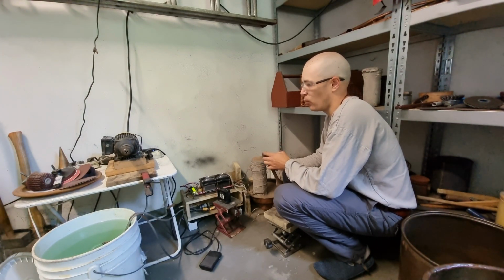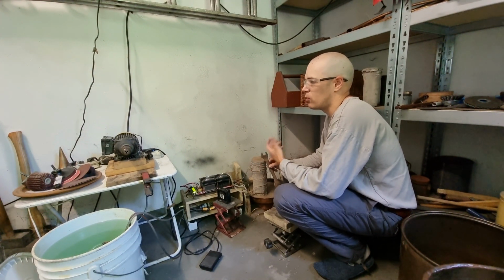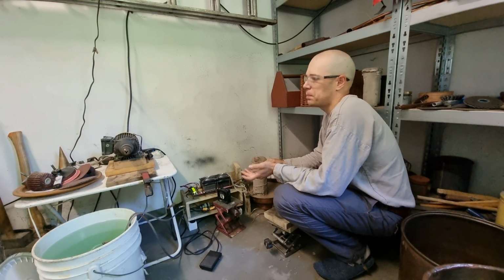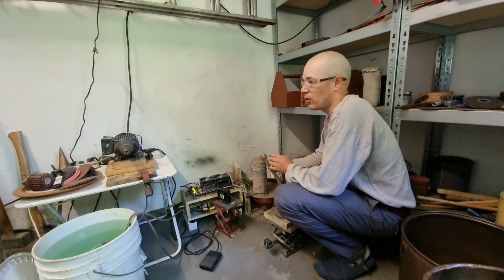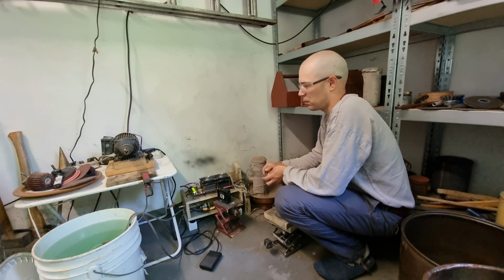So that of course takes much longer time. At about 24 hours, we see about 1 millimeter of burn off, and then it starts to become slower and slower and slower. But yeah, that is really just like an add-on. Already the black heart malleable cast iron is a really tough material, good for almost all purposes, and sees widespread use in industry even nowadays.